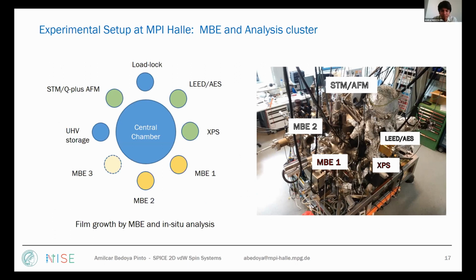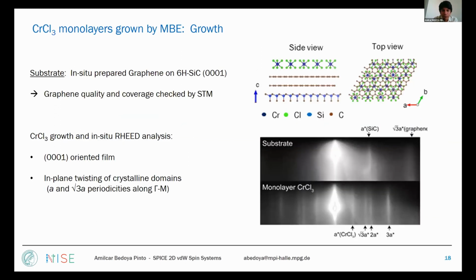So then, just briefly to mention how we prepare the samples. We have two MBEs attached within an in situ cluster, with, of course, an STM and other surface techniques. Very important here is that once we prepare the sample, it never sees air. So it is everything ultra high vacuum for all the characterization that I'm going to present in this talk.